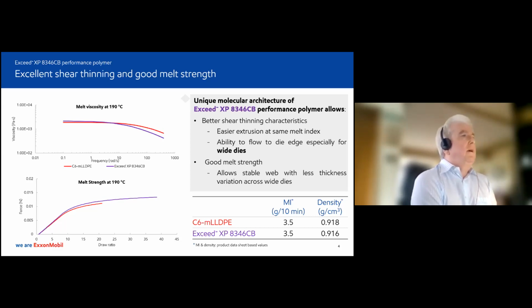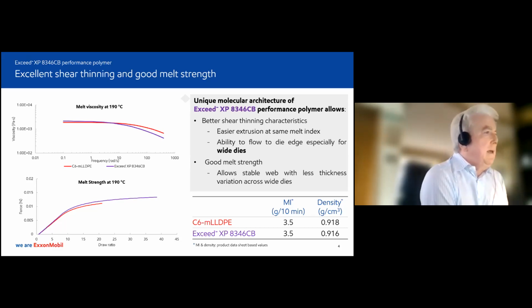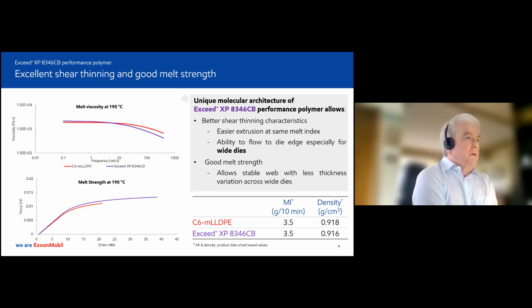And I have two graphs here to show you that, firstly, compared to, shall we say, a conventional C6 metallocene resin of similar melt index and density, it shear thins a lot more in the extrusion shear rate region. So that means that you're going to have easier extrusion. And it's particularly useful for customers that have wide dies, because the resin therefore is allowed to flow more evenly and better into the sides of the die. Also, the melt strength is a little bit better. And now melt strength is something that we normally associate with blown film, but in cast film, it's also very important, because what it does is it stabilizes the web. And it means that if you can stabilize the web, you normally get less thickness variation. Of course, it's very important to have as good a gauge control as possible, and to make sure that you have less thickness variation right across the web, particularly on the wide dies.